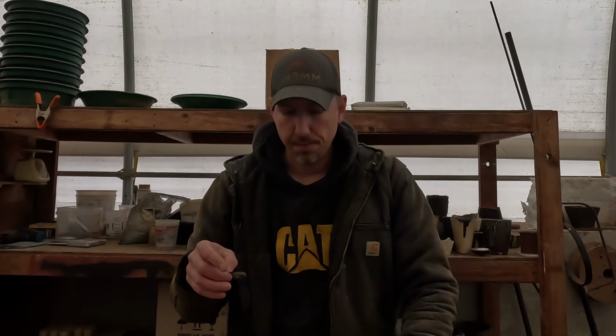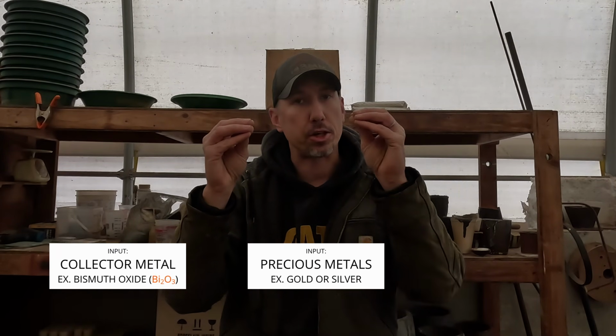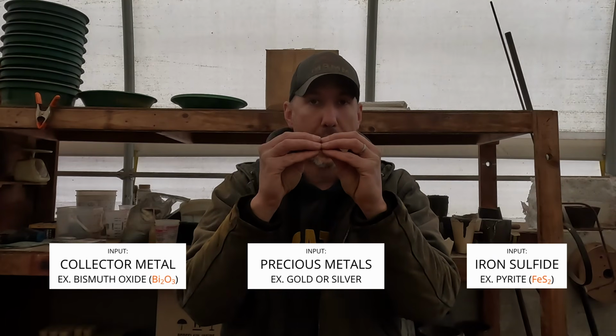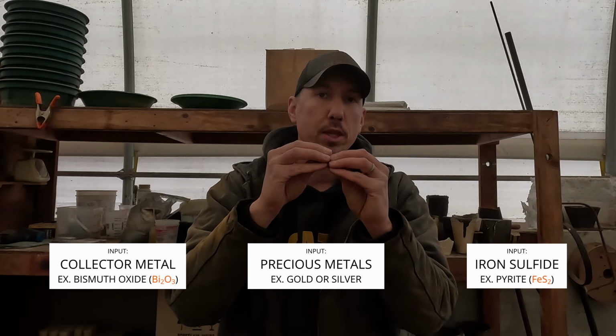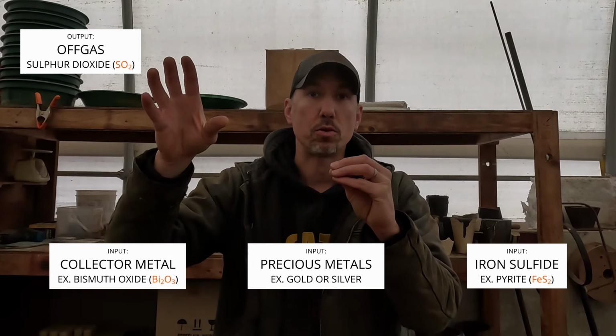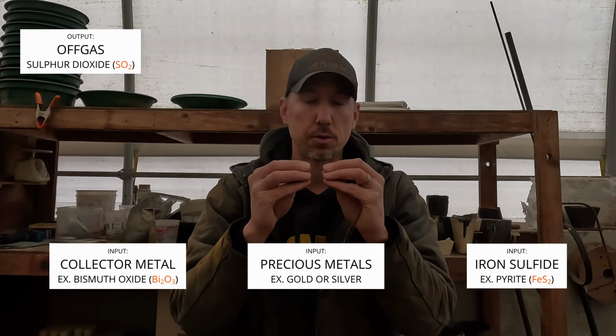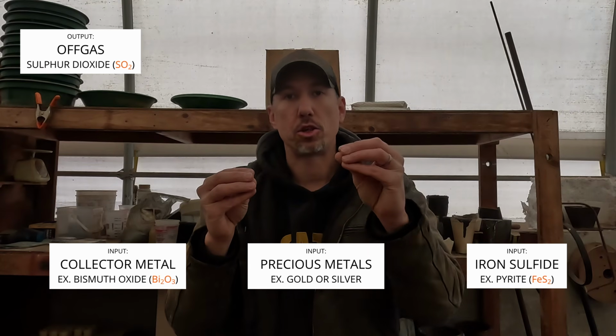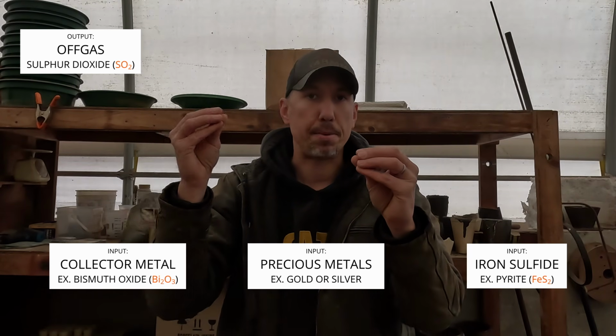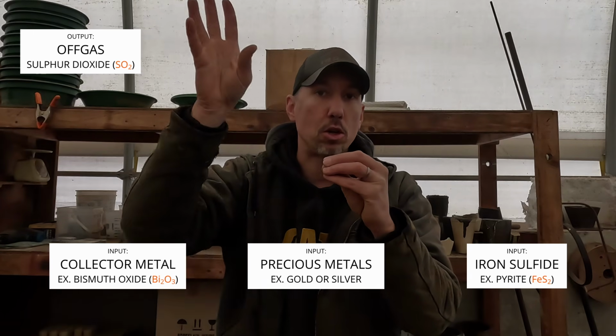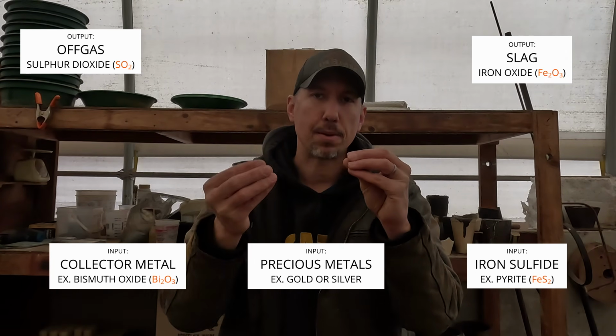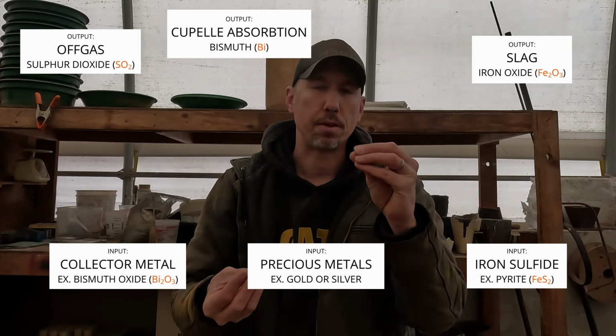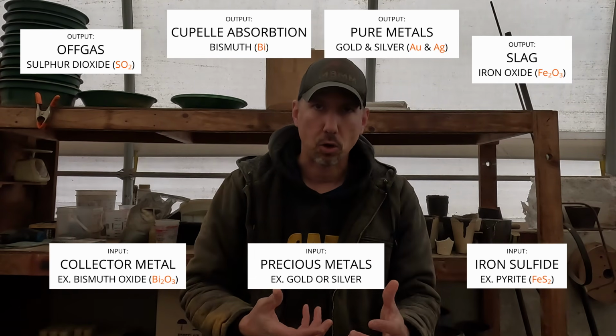Now, why do I use bismuth oxide instead of bismuth metal? Because it's an oxide, the bismuth oxide is reactive when it comes in contact with sulfides. So this will act a little bit as an oxidizer in our smelt. As you have the bismuth oxide and a sulfide particle in the flux, they connect, the oxygen combines with the sulfur and drives it off as SO2, and it will convert that sulfide to an oxide. So for example, if this is iron sulfide, pyrite for example, and bismuth oxide, those will connect to form SO2, iron oxide, and it will convert the bismuth to bismuth metal that will then come down through the flux and collect at the bottom, collecting gold and silver along the way.